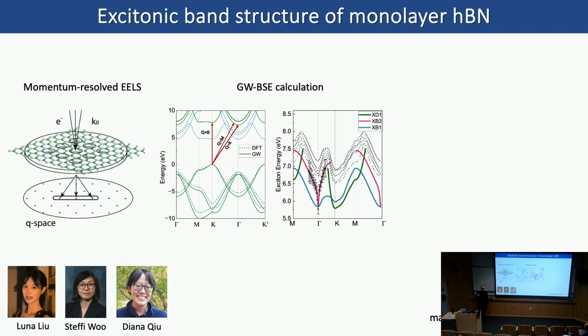But when we add the exciton effect, the binding energy of the exciton, into this, we found that actually the Rydberg state at this q level has a larger binding energy. So the energy shift of a real exciton is actually more than this part. This is an excitonic band structure, which marks the gamma point. So these actually mark the momentum of an exciton. Gamma means q equals 0, K means q equals K, and they're almost identical. It's hard to distinguish which one has a higher energy and which one doesn't.